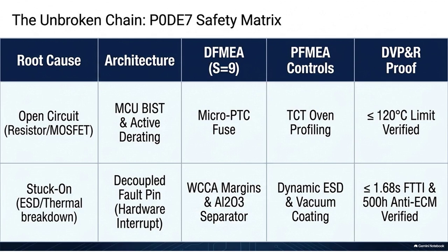The polymer has to expand, sever the carbon chains, and choke off the current rapidly enough that the absolute maximum temperature on the board never exceeds 120 degrees Celsius. If it hits 121 degrees, fail. No carbonization, no melting, no fire allowed. The hardware has to contain its own destruction perfectly.